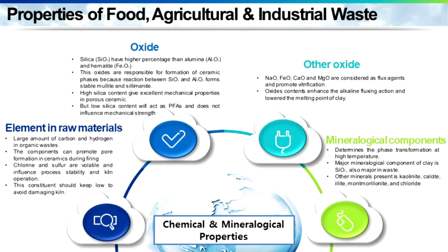The presence of other oxides in the waste materials such as sodium oxide, iron oxide, calcium oxide and magnesium oxide are also considered as flux agents and promote vitrification during the firing process of the porous ceramic. In other words, oxide contents enhance the alkaline fluxing action and subsequently lower the melting point of the ceramic. The mineralogical components of waste, which determine the phase transformations at higher temperature, are also important. It helps in predicting possible phase transformations during the fabrication of the porous ceramic.